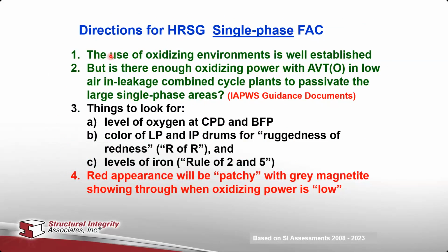I've already mentioned a couple of times that you have to use oxidizing environments. Do not use reducing agents or reducing treatment. Things to look for would be the level of oxygen at the condensate pump or the boiler feed pumps. You want the LP and the IP drums to be ruggedly red, and that would give you an indication that you're operating on an oxidizing cycle.